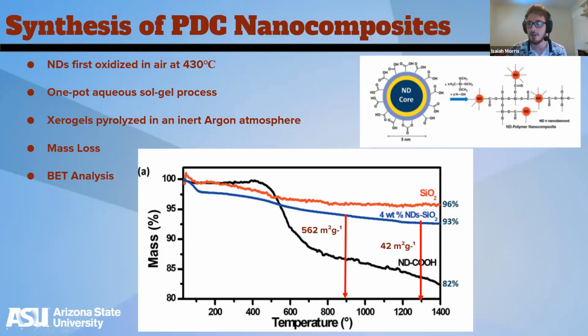So obviously that material would have to be more dense. And that's what I thought as well at first, but this couldn't be farther from the truth. As you pass that glass transition state, the glassy state silica becomes more viscous and more amorphous and expands. And actually these 0D nanomaterials end up attaching themselves to the surface of these large inflated silica molecules, actually causing macroporosity instead of mesoporosity. So it's not that this material is more dense, it is just that it has bigger pores instead of a bunch of smaller ones.